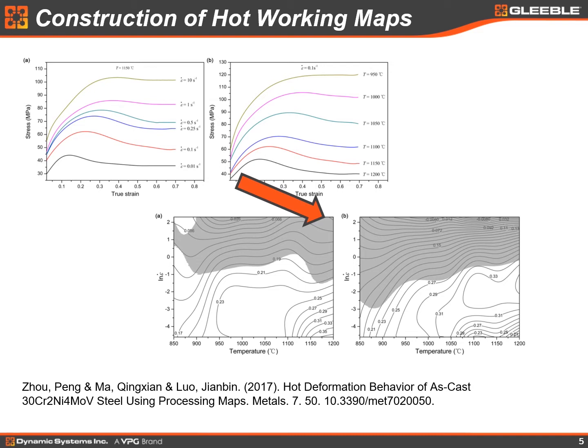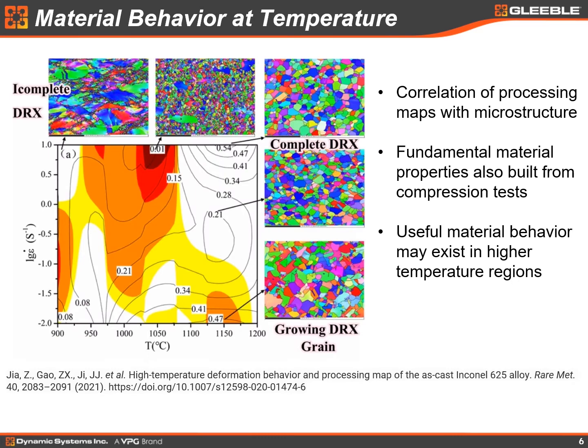And you'll see that in a lot of these diagrams there is a limit as to how high the temperature goes, how high we can operate in generating these types of data. Shown here is another very good example showing these process maps generated from Gleeble work, in this case on Inconel 625 nickel-based superalloy. The micrographs here also show the complex, multifaceted microstructural processes going on at different temperatures and strain rates. At too low of a temperature and too high of a strain rate, we don't get any dynamic recrystallization, and an accumulation of deformation and strength would eventually lead to cracking at higher strain values. Conversely, at too high of a temperature but too low of a rate, we get unwanted grain growth, and complete dynamic recrystallization is only found at elevated temperatures and high strain rates.